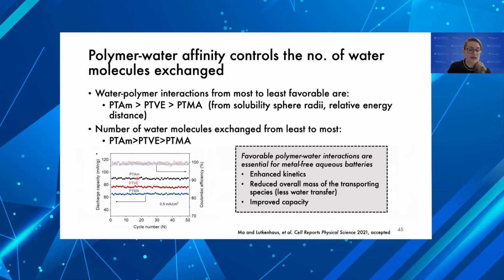So PTAM, which has the best water interactions, has a discharge capacity of 90 milliamp hours per gram, whereas PTMA, which has the worst water interactions, has a discharge capacity around 75. So this is saying that you can have really large changes in performance by just adjusting the backbone and linker group, where the design criteria now are telling you to pick a polymer that has favorable polymer-water interactions. And by doing that, the benefit is that you get enhanced kinetics, reduced overall mass of the transporting species, and that gives you improved capacity.